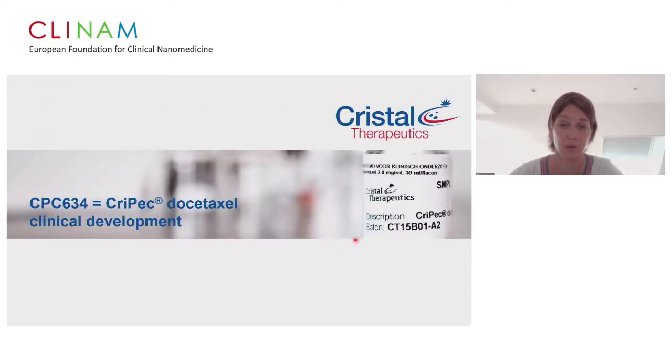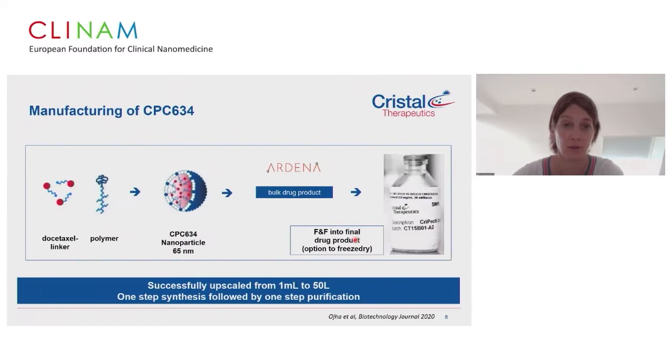So this is the system that we've developed, and now I'd like to guide you through the clinical data that we've obtained with the lead product, CPC634, which stands for docetaxel, entrapped with the same approach: linker plus polymer, creating the 65 nm nanoparticles. We successfully upscaled the synthesis together with Ardena, so that's really clinical scale. And we by now also demonstrate that we can nicely make a freeze-dried product, although the clinical batches were a frozen solution, which had a stability of more than 5 years.